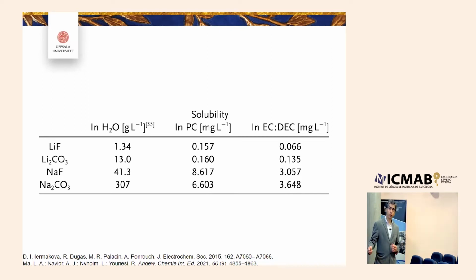So if you go with inorganic, the problem is that most inorganic species in sodium-ion SEI are more soluble compared to lithium-ion SEI.